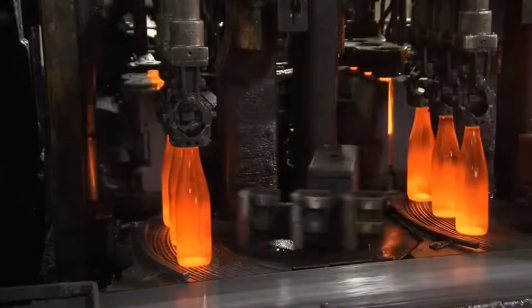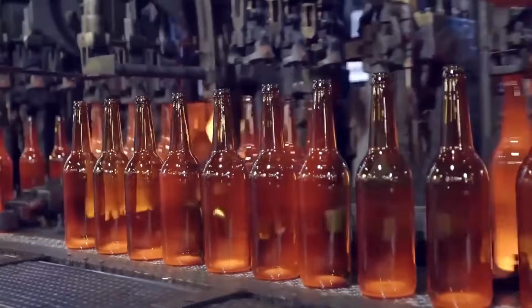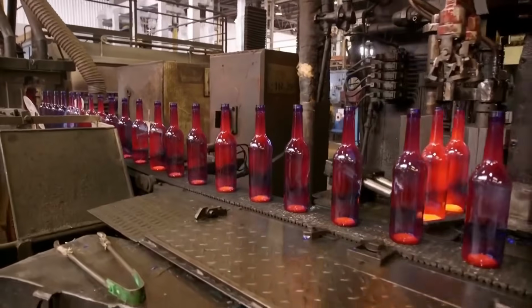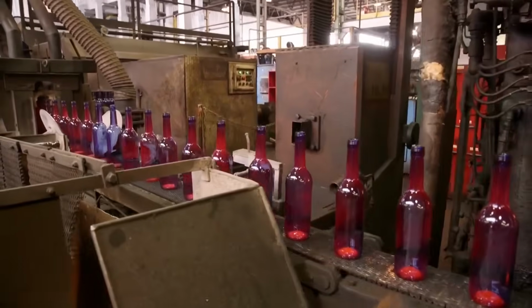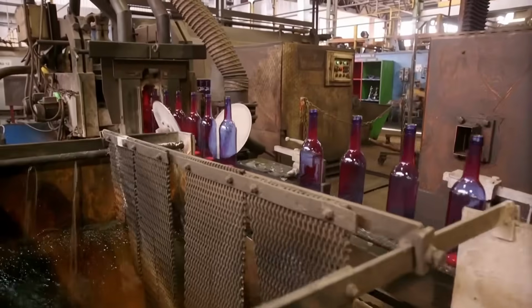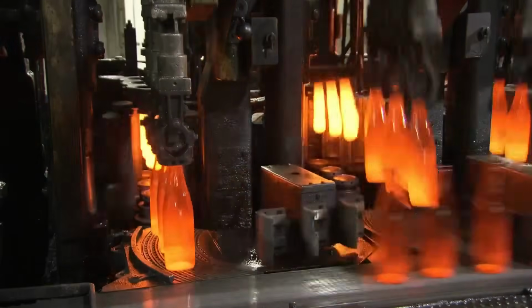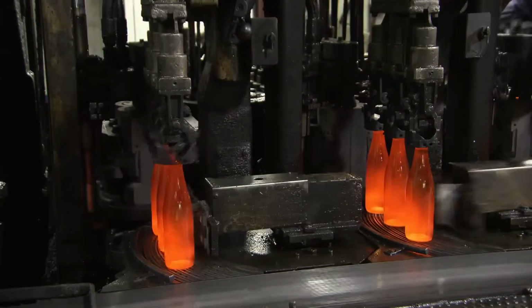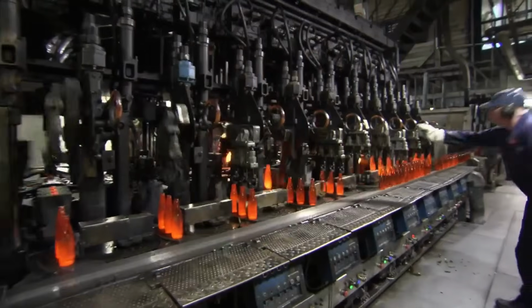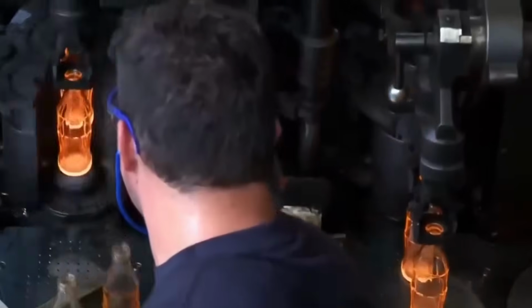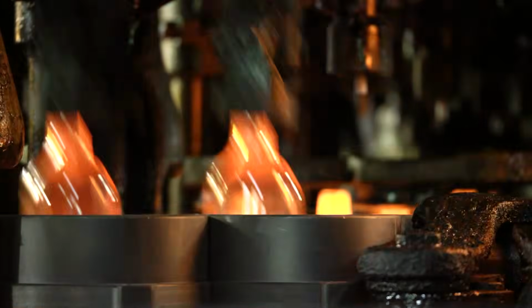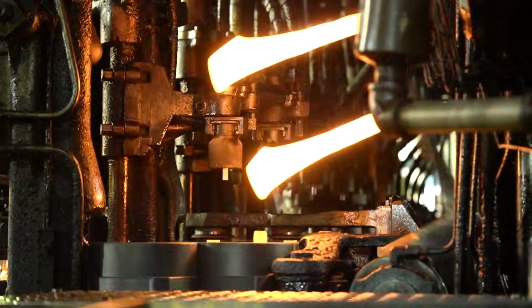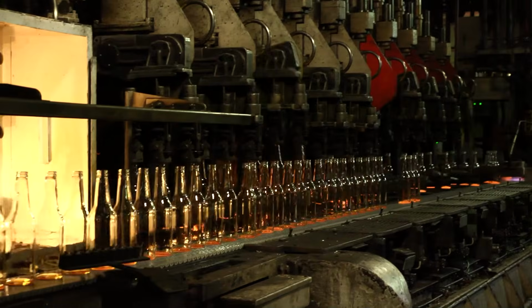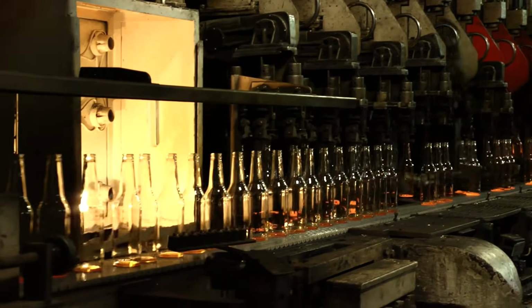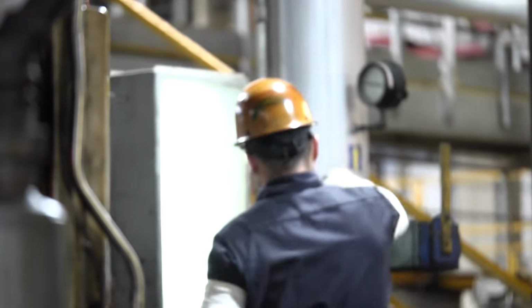Color is controlled during melting. Small amounts of iron, sulfur, and carbon darken the glass. This is not aesthetic. Dark glass protects beer from light, preventing degradation before it reaches the consumer. A mistake here affects the product, not just the container. To prevent molten glass from sticking, mold surfaces are coated with graphite. Without lubrication, bottles would crack or tear instantly. The system depends on every mold performing flawlessly, cycle after cycle.